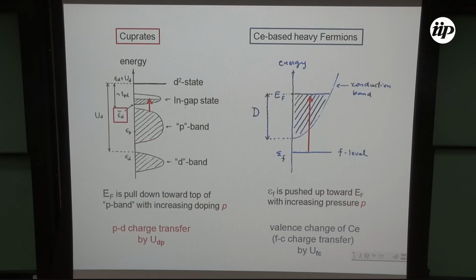So in the cuprate, the Fermi energy is pulled down toward the top of the p band with increasing doping p. This is a very similar effect to that in the cerium-based heavy fermion, where the f level is pushed up toward EF with increasing pressure P. So the effects of pressure and doping are similar in both systems.